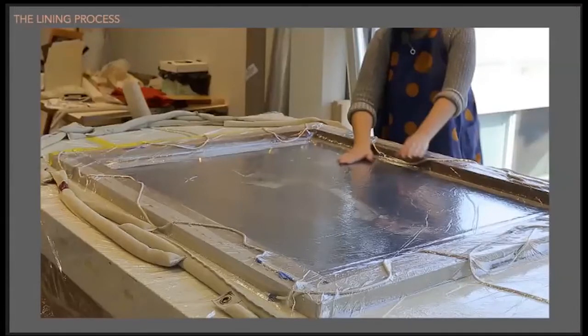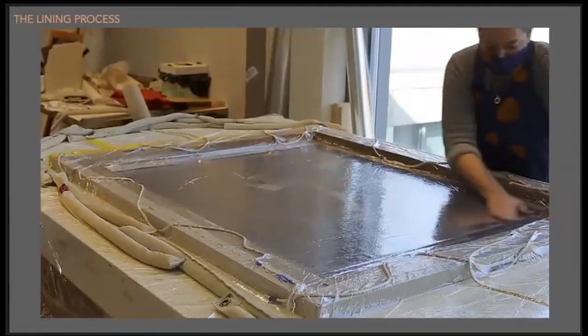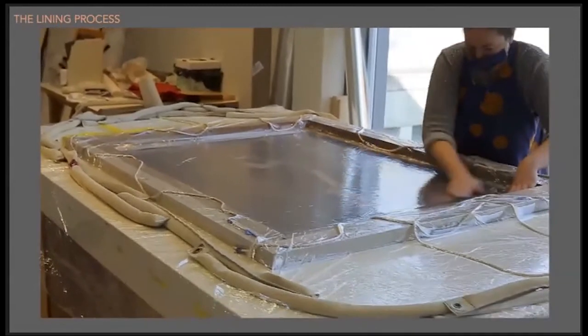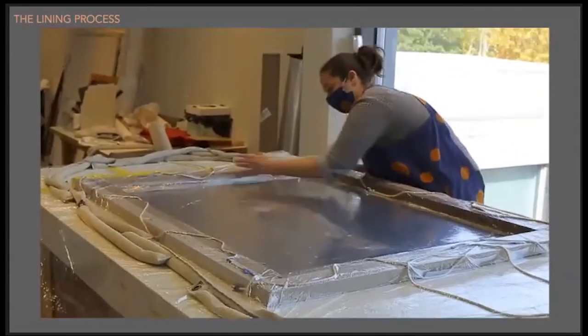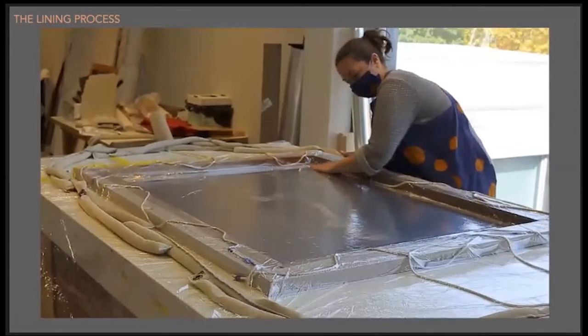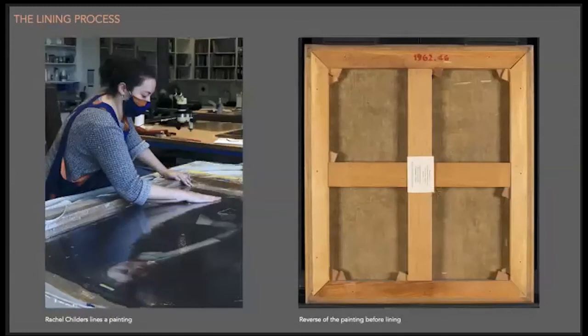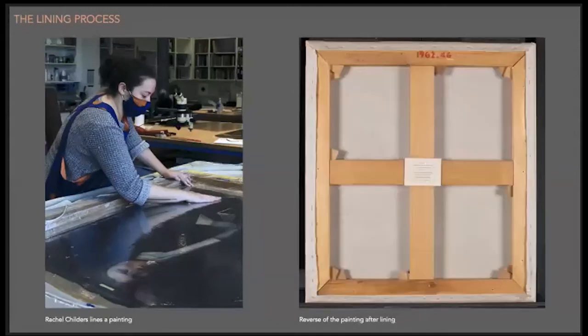While I won't go into detail on the delining and lining process, as that was so elegantly covered by our colleague Mary Holland last week, I want to mention that the collection of Nehemiah Partridge paintings underwent the same condition treatment. I'm shown here during the relining of Partridge's portrait of Jacob ten Broek, ensuring an even vacuum prior to turning on the heat that activates the adhesive, generating a bond between the original canvas and its new secondary support. Here's the verso of the painting on the right prior to lining, showing the wax-infused lining support. And after the painting was lined to a more sympathetic fabric, the verso appears both structurally and aesthetically improved.